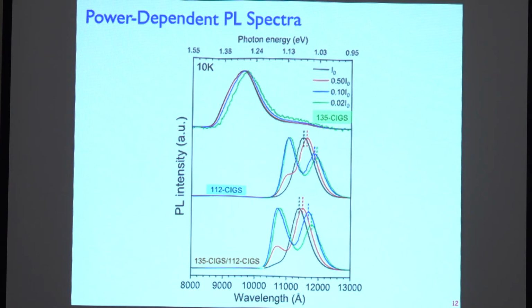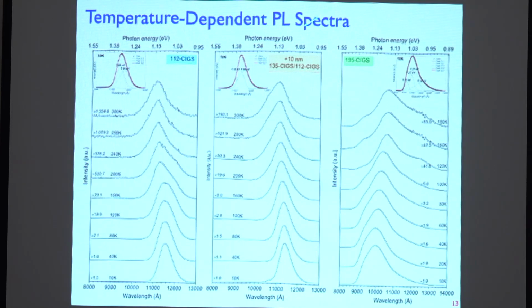Similarly, for the 112 that has a thin layer of 135 on top of it, the nature is quite similar to 112, but we don't see any emission from 135, so we don't see the signature of 135 in this bilayer system. Now, when we do the temperature dependence, for example, we measure the PL from 10 Kelvin up to room temperature of 112. You can see the peak shifted to shorter wavelength. This is called a blue shift, which is the nature of a P-type semiconductor, as well as the sample that we have, 10 nanometers of 135 on top of 112.